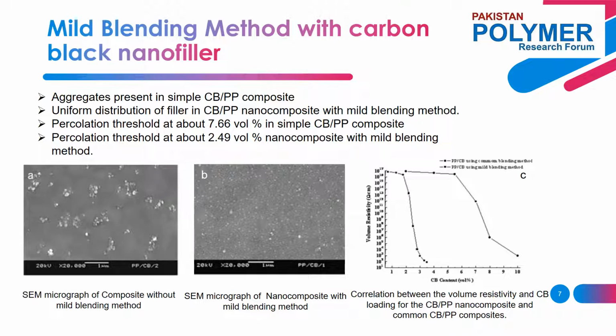When the carbon black content reached the percolation threshold, the effective tunneling zones of the nearest neighboring particles overlapped and tunneling conduction occurred. Overall, this research shows that nanocomposites can be fabricated successfully by compounding polypropylene with the nano carbon black aqueous suspension using the mild blending method.